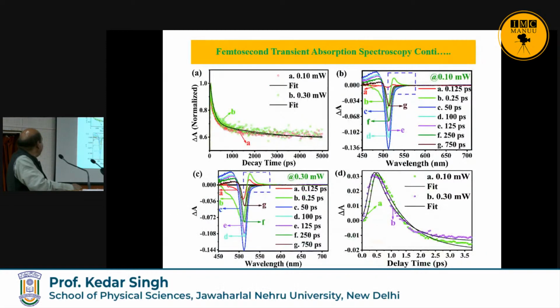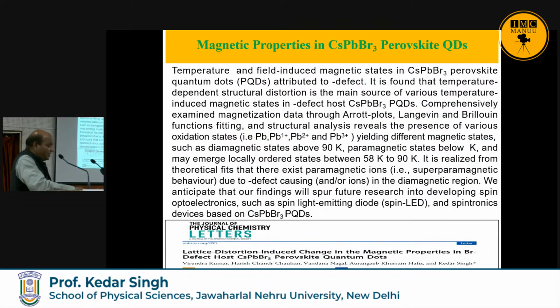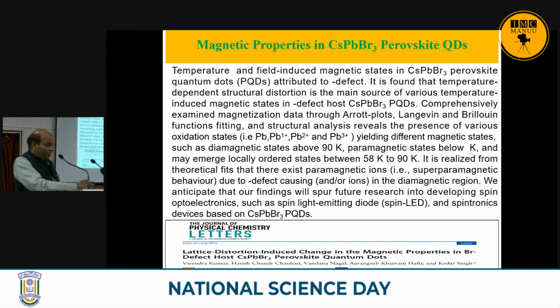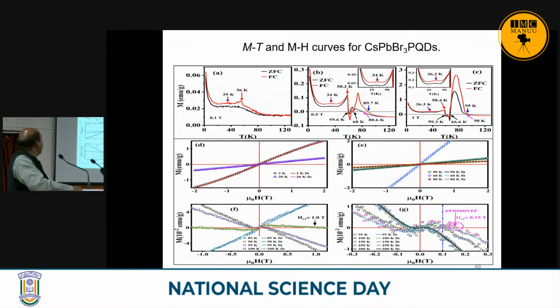Just I want to show you this application. Then we did some magnetic measurement on the CsPbBr3 perovskite quantum dot. Normally quantum dots should not show any magnetic properties because this is a diamagnetic material, but due to some defects it is showing some magnetic property. How will we investigate this? Just if you see, yes, this is the M-T curve. You can see this is the temperature versus magnetization. Then this is the different temperature.